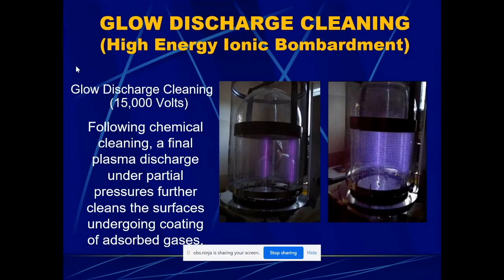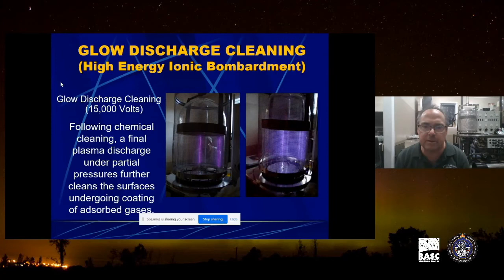During the pump down, we do what we call molecular sandblasting, which is like an ion plasma discharge, where we apply 15,000 volts to the residual atmosphere. This bombards the surface of the glass with ions, so that it basically rips off any water molecules, because a lot of water likes to stick to things. It's like if you ever take a propane torch to a piece of glass, you'll see the moisture dissipate, and then when you remove the torch, you'll see the water reform right back on the glass. We have to get rid of this water, otherwise the coatings won't stick very well to the substrate. So this plasma discharge is used for a good 20 minutes, and it rips off all those water molecules, making the glass substrate perfectly dry.